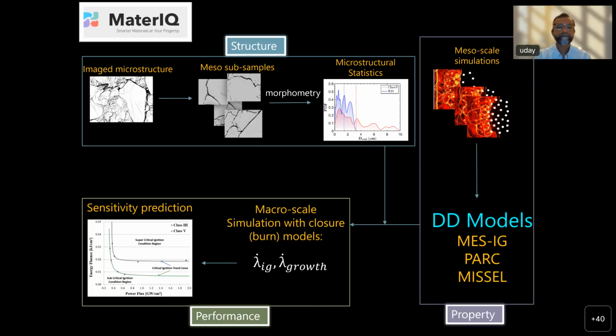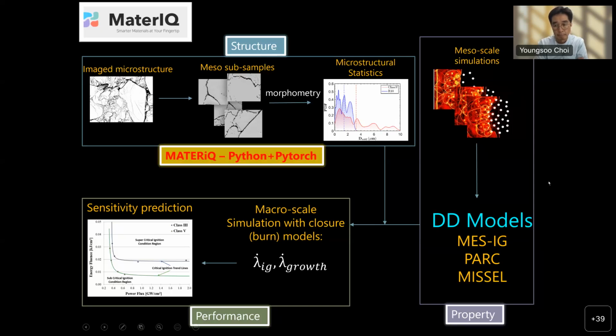Okay, we have another question in chat room by Cooper. He asked, did you look at the difference in the surface area for the critical versus non-critical voids? Surface area. No. We looked at diameter and aspect ratio. It is not terribly sensitive to the aspect ratio. It is sensitive to the diameter. So the surface area does matter. And in fact, this is common knowledge. The specific surface area does matter. So the smaller voids tend to be more sensitive than the larger voids for a given aspect ratio.